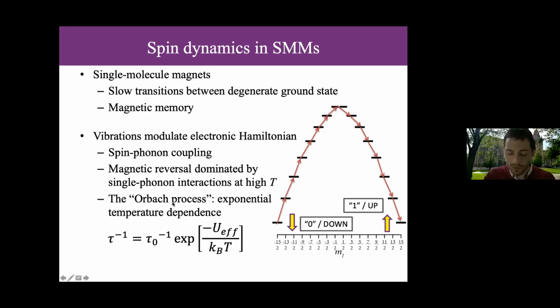So a note of possible confusion for the students in the audience. This is often described, the Orbach process, as a multi-phonon process. And as a whole, that's true. But just to keep in your head that this is all occurring from single phonon absorptions and emissions. So it's a multi-phonon overall process that is actually underlyingly run by single phonon events. Okay, so there's not necessarily any correlation between phonons that are being absorbed here and here or emitted over on the other side. Okay. And this leads to an exponential temperature dependence that is just like the Arrhenius law, which you will all well know.